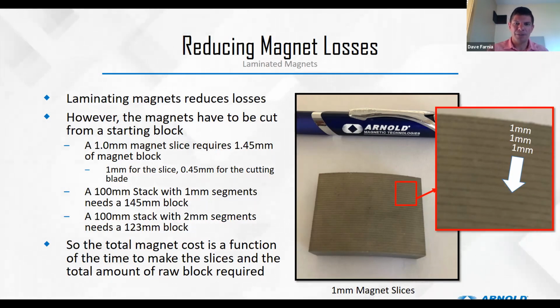So the cost for that finished magnet, the finished laminated magnet, is a function both of the time to make the slices and the total amount of raw block that's required to generate that finished magnet segment. And we can think about this too. Besides having more block requirements for those thinner segments, we've doubled the number of cuts. So to go from 2 millimeters to 1 millimeter, it's twice as many cuts. So the time to process that magnet block is also going to be nearly double.